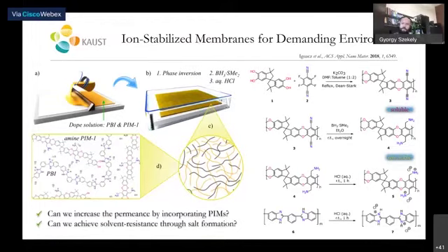But the initial one here, this is soluble. So that's a key point here, that when you use the originally reported PIM, it's soluble, which means that the membrane is dissolved in the solvent.